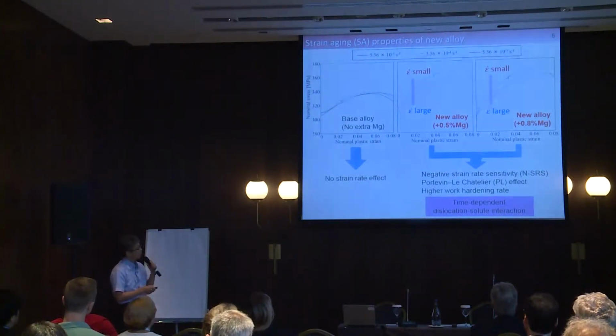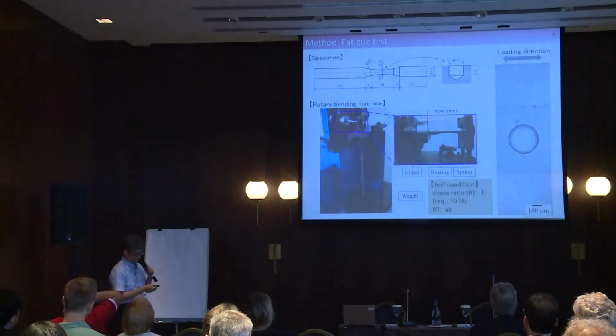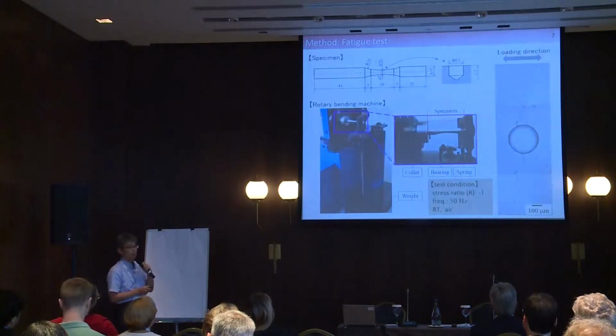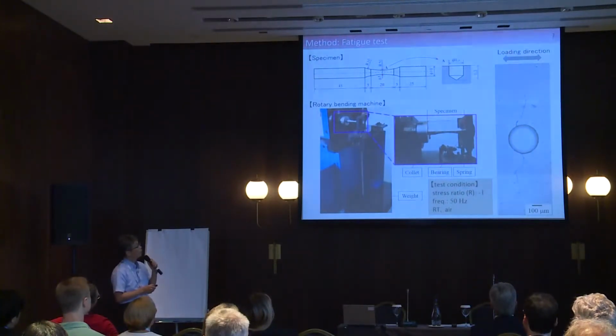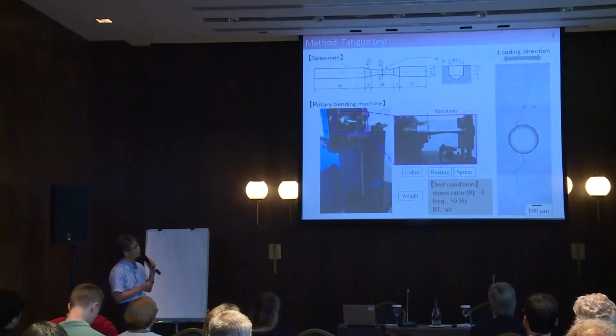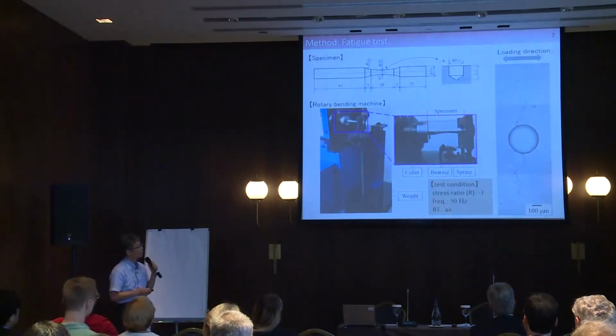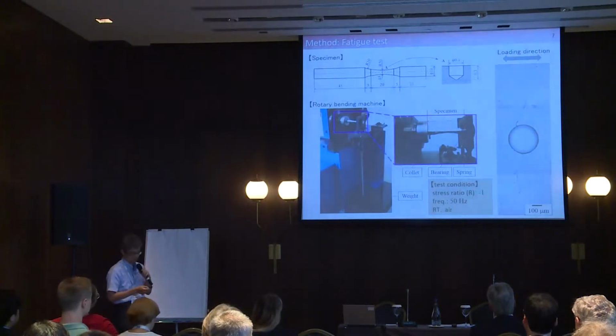Then we conducted fatigue tests by using these special alloys, new alloys. We fabricated this fatigue specimen and introduced a small blind hole here for a crack starter. And we used a cantilever type rotary bending machine, and used this test condition to see the fatigue behavior.